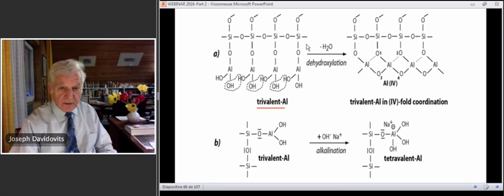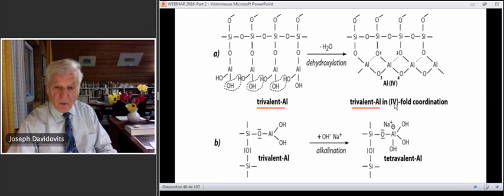This is the kaolinite molecule with the OH. So we have Al, O, OH, OH, trivalent. With the dehydroxylation, we end up with the oxide. Aluminum is trivalent, covalently bonded to oxygen, but it is in 4-fold coordination. The aluminum is surrounded physically, not chemically, by 1, 2, 3, and 4 atoms of oxygen. It is trivalent, Al3, and the coordination is 4.